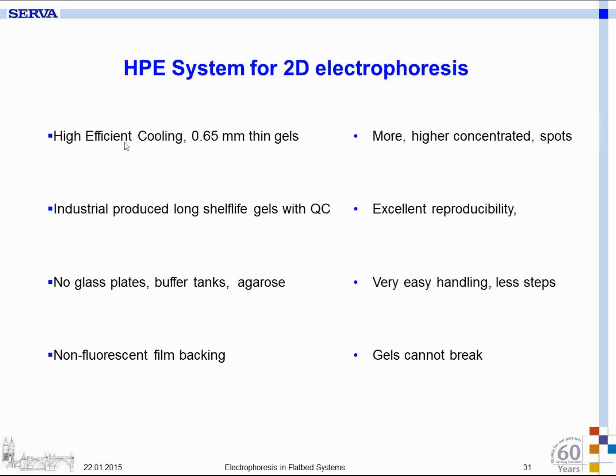So why is it called HPE system, high performance electrophoresis? First of all, because of the relatively thin gels and the film support on the cooling plate, you get more and higher concentrated spots. The gels are produced for a long shelf life, so they don't change their separation behavior, and you can achieve excellent reproducibility because they are made with quality control in an industrial way, which is different from lab cast gels. I can tell you there are papers already around which have proved that.